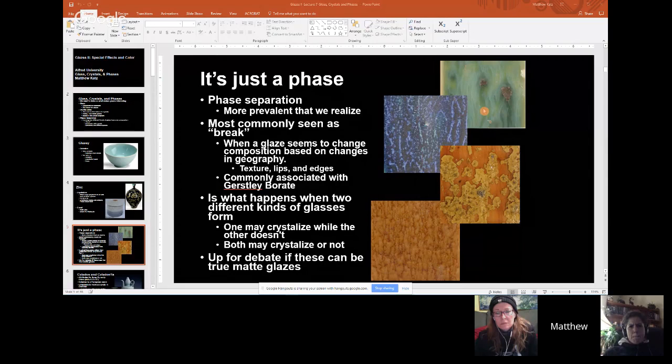Specifically, titanium will force crystallization, and this becomes one of those things that, when I talk about glazes and the UMF and all that, people say, "Oh, well, here's a glaze that's a matte glaze, but it's not in the matte region." 9 times out of 10, I look at that formula and it's got a ton of titanium in it. Well, titanium just naturally will crystallize or phase separate on its own. If you have enough titanium, it'll make a glossy surface look matte. It doesn't mean it's violating the rules of Stull. It's just that titanium wants to crystallize. It does that. That's just what it does.